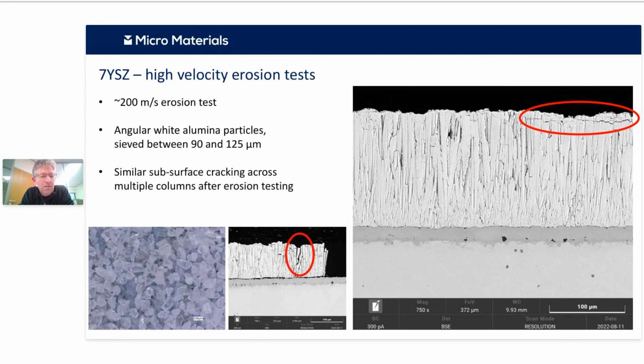So the two main mechanisms that you see are this cracking across the columns, and you get in some locations as well, you get this transition to this more severe mechanism where the whole structure fails. So these are exactly the two mechanisms that we see in a small scale test. So that's for the first time we were able to see that. That's quite nice.